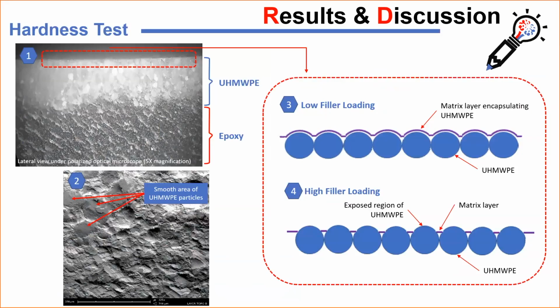The incorporation of ultra-high molecular weight PE in the epoxy system seems to produce two distinctive layers, which can be seen from this figure 1, taken from a lateral view under a polarized optical microscope at 5 times magnification. This is as predicted, due to the difference in density of epoxy and ultra-high molecular weight PE, assisted by the reduction in viscosity of the epoxy resin by acetone.